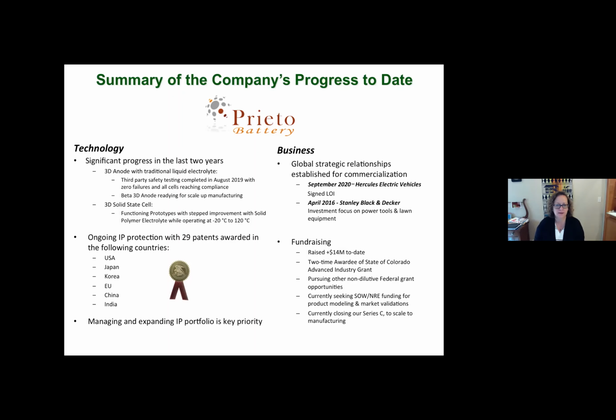And so in the last couple of years, we've finally been able to develop good prototypes. We did package our 3D anode with traditional liquid electrolyte, normal separator, and normal cathode laminates to have some third-party safety testing completed. And that was really important for demonstrating the stability of the chemistry of the anode. Now we're focused on doing the same thing with our fully integrated 3D solid-state cell. It does function over a broad temperature range, and we focus quite a bit on the patents. So the IP protection is the major use of proceeds for the company right now.